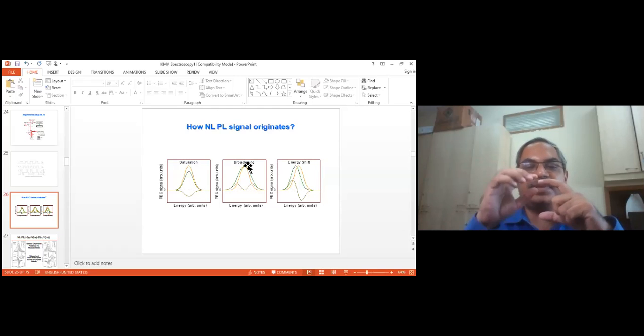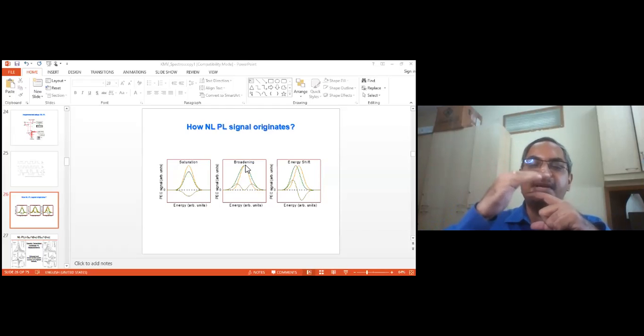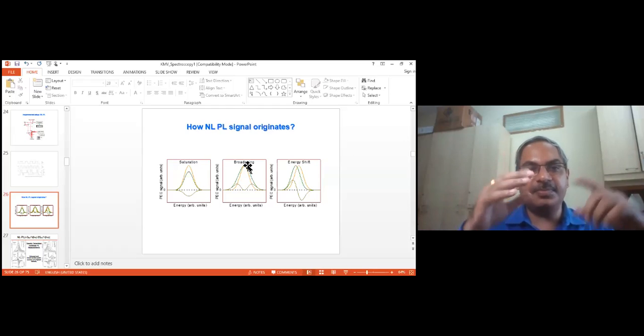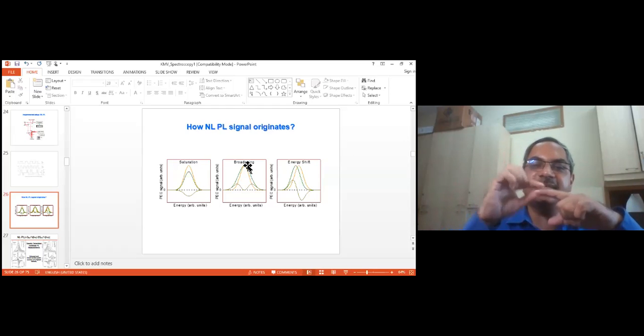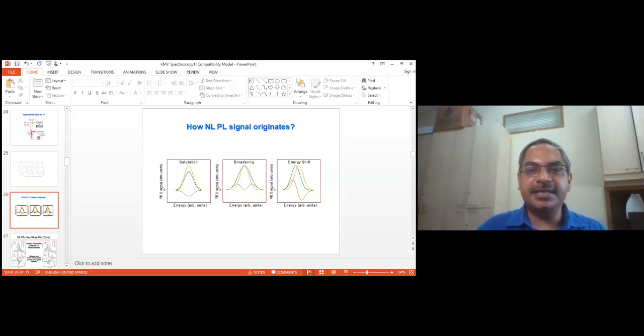Sometimes this energy level basically broadens. They're too closely spaced, or there is some interaction which causes this broadening of the energy level, which means more density of states, more closely spaced energy levels. In which case more and more electrons can be excited, occupying a band of energies instead of one single energy level. So that leads to broadening. Or sometimes this energy level can shift. So depending on the process, saturation or broadening or energy shift, you can have different signal shapes.